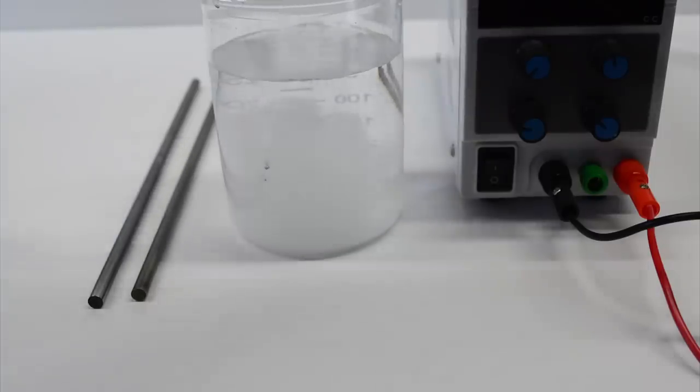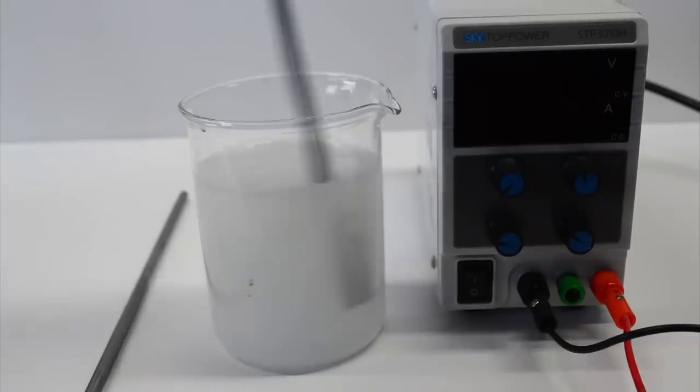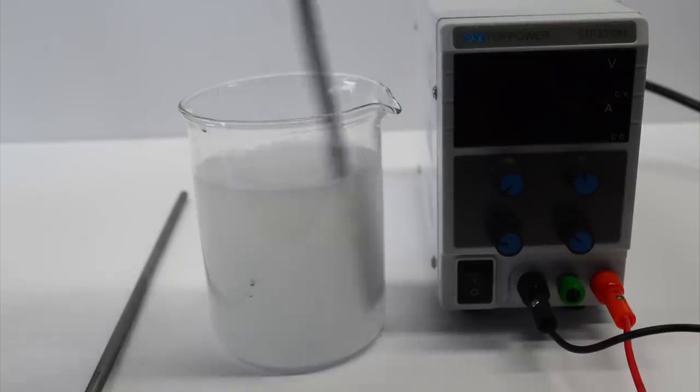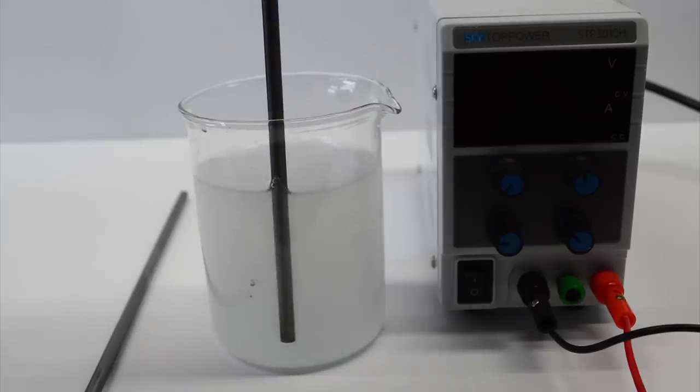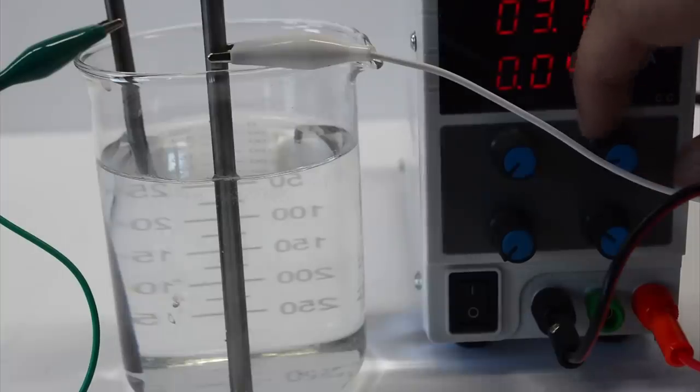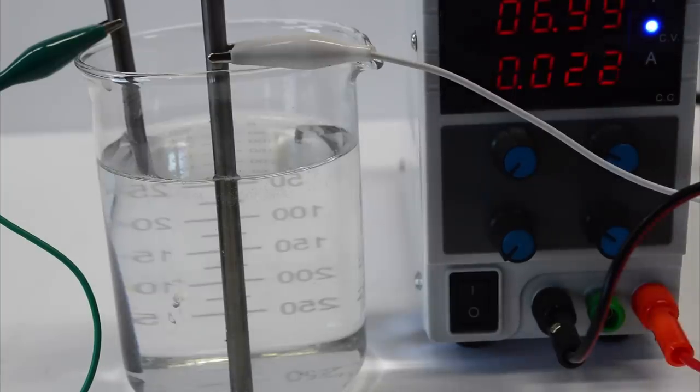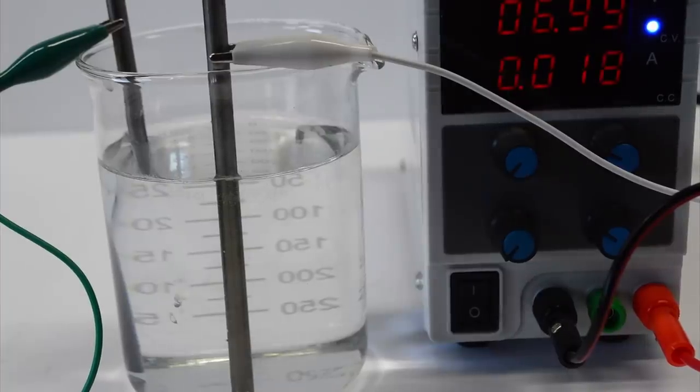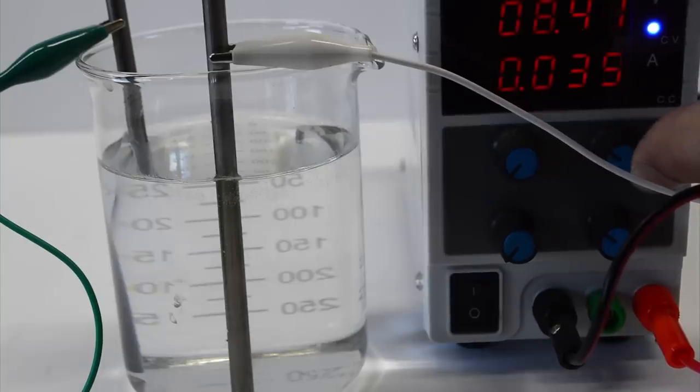Here I'm using a solution of sodium carbonate, also known as washing soda. I didn't use any particular amount, and I literally just threw some in. The electrolyte doesn't even really matter, and this will work with just about anything, but I would avoid things with chloride in them. Not because it'll interfere, but because you run the risk of releasing a bit of chlorine, which is definitely not good for you. Hence the choice of sodium carbonate. I've prepared a piece of titanium by first sanding and cleaning it, and then connecting it to the anode, which is the positive wire of my power supply. I'm using another scrap piece of titanium for the cathode, and both are simply placed into the electrolyte solution. When we turn on the power, very quickly a layer of oxide will form on the titanium. But once that oxide layer forms, it very quickly stops growing as the layer itself inhibits the reaction. To grow a thicker layer, we need to increase the voltage.